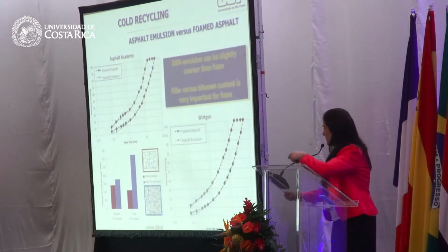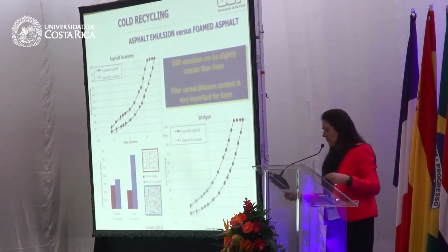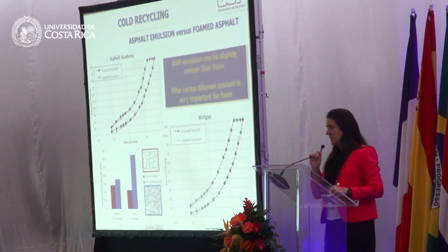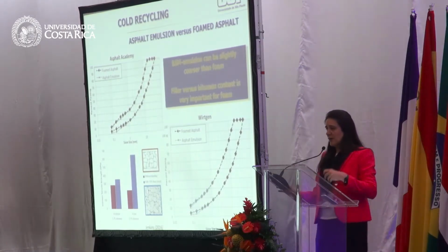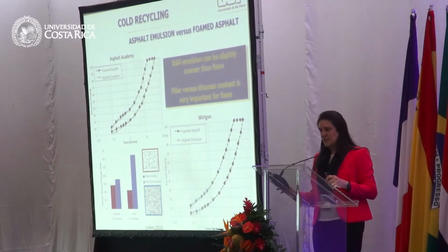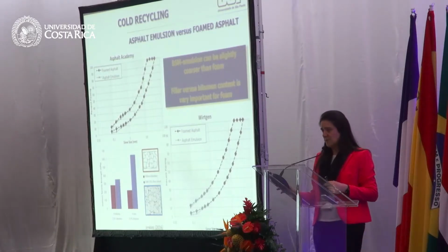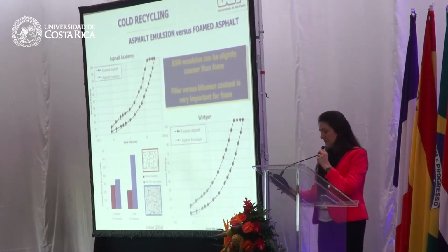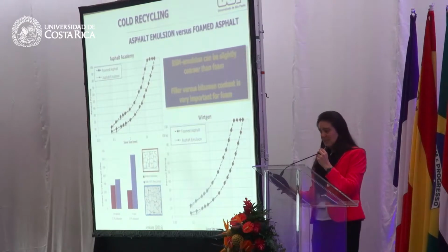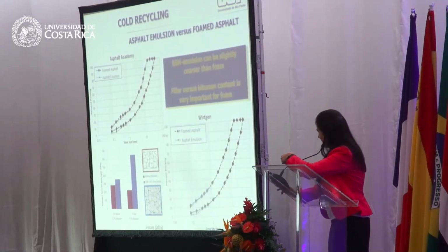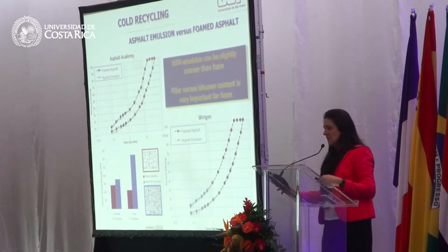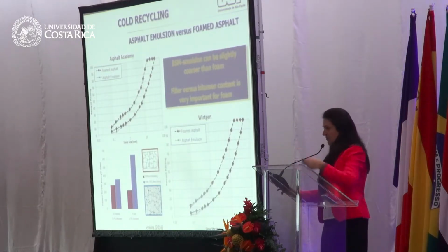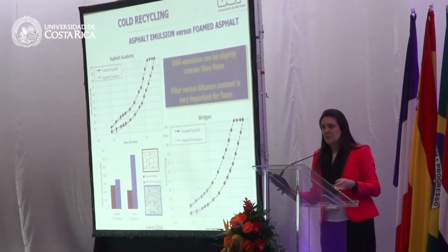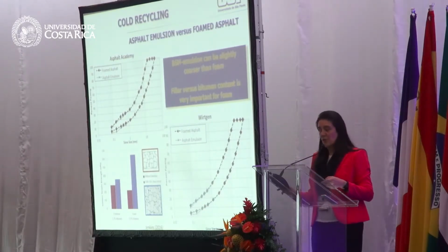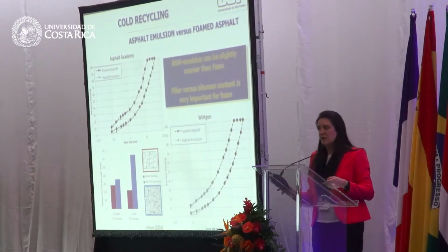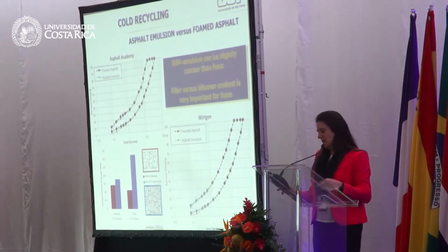So this picture here I like a lot. It's from Professor Kim Jenkins from Stellenbosch. He is running a lot of research on cold recycling, especially in the foaming process. We have close contact with them. And in this picture, we see clearly the influence of the fines. Not too much for the emulsions, but a lot for the foamed. So if you decide to run your cold recycling with foamed asphalt, you have to take care of the gradation of your aggregates.